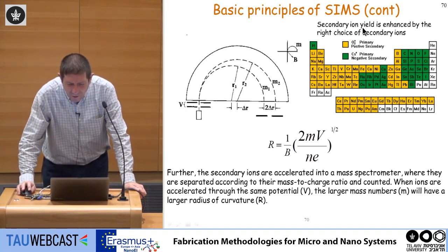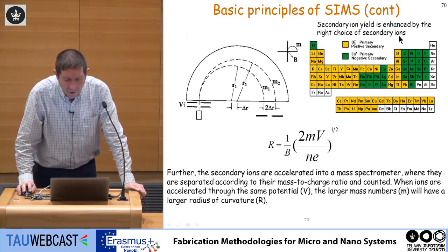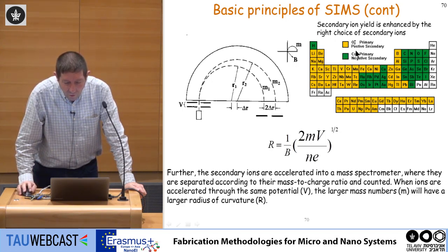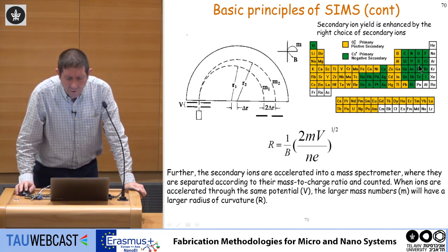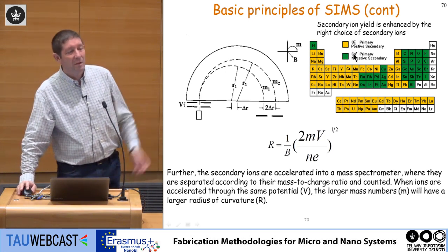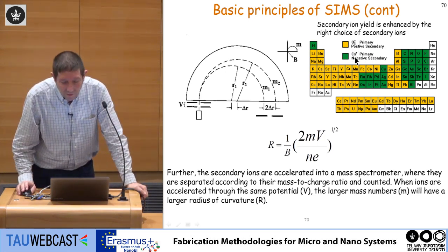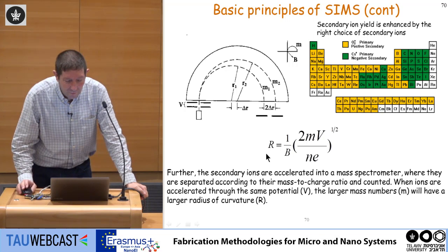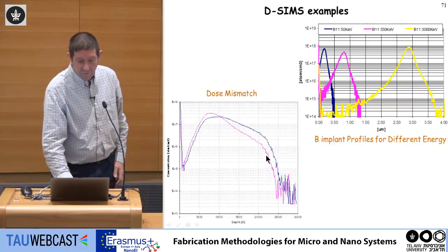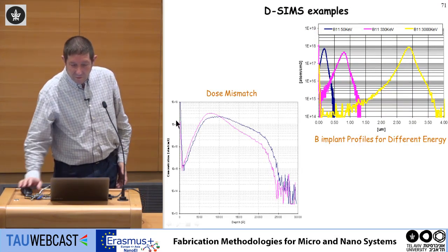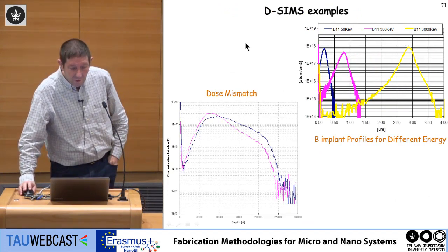The secondary ion yield is enhanced by the right choice of the primary ions. I can use oxygen primary or cesium primary. This is the periodic table. I can use oxygen as the sputtering ions. I can use cesium as the sputtering ions. These are typical examples for this effect. And this is a typical D-SIMS example.